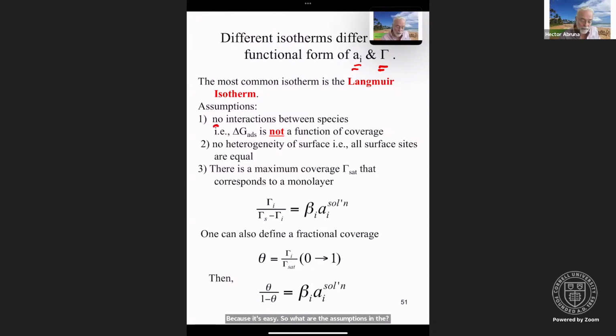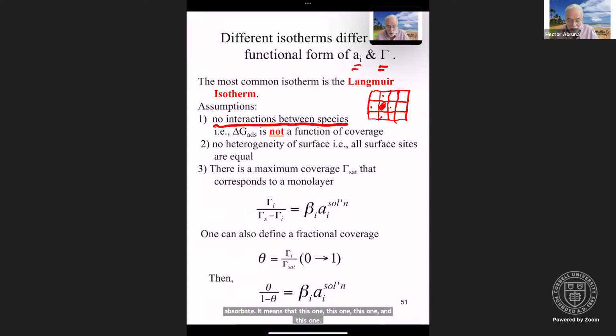It assumes no interactions between species. Translation: the free energy of adsorption is not a function of coverage. So for example, if I have a surface, let's say with 9 sites, if I occupy this site with an adsorbate, it means that this one, this one, this one, and this one, their free energies of adsorption are not affected by the presence of this guy. And we almost intuitively know that that can't be the case, but we assume that it is, okay? That is, the free energy of adsorption is not a function of surface coverage. We'll see later on isotherms that take into account such interactions.